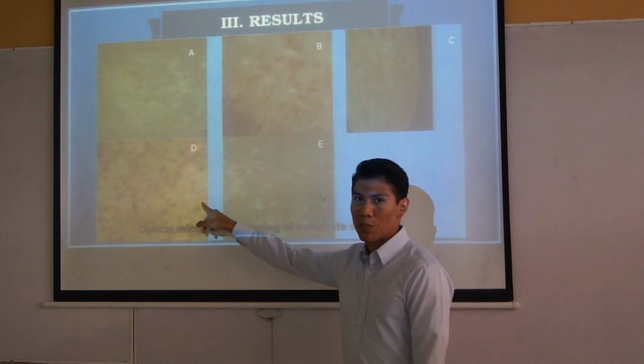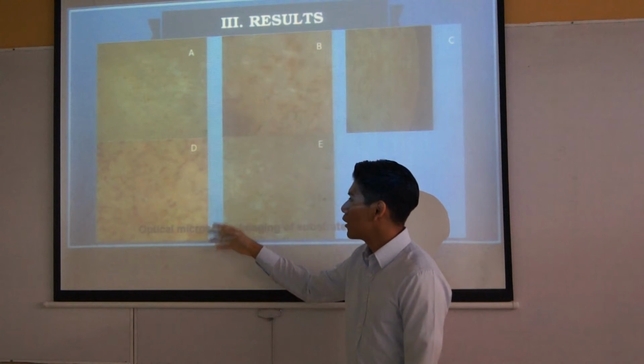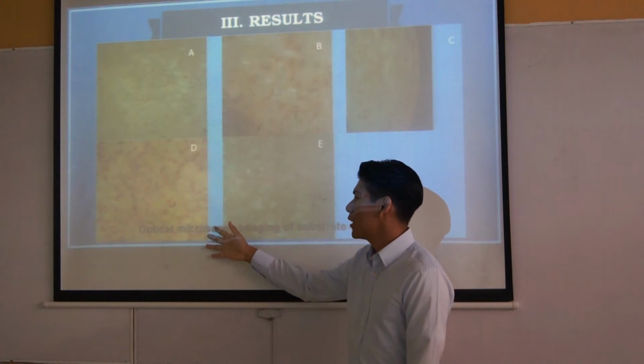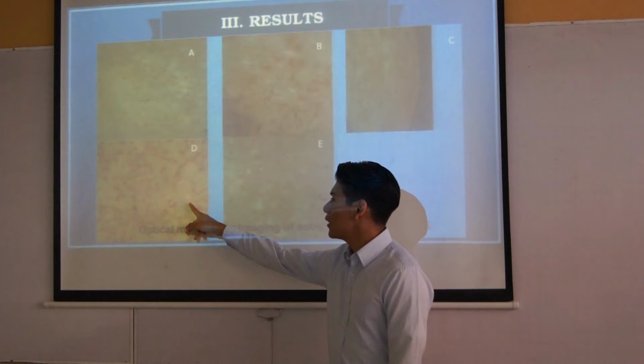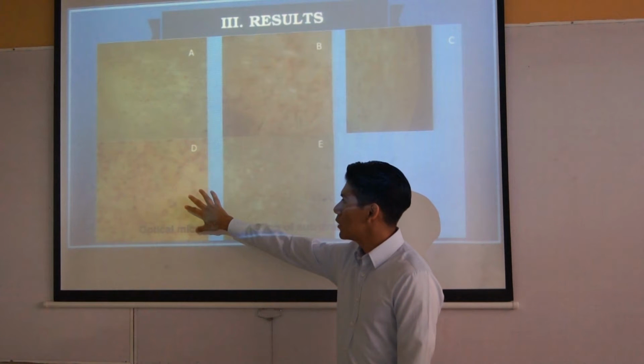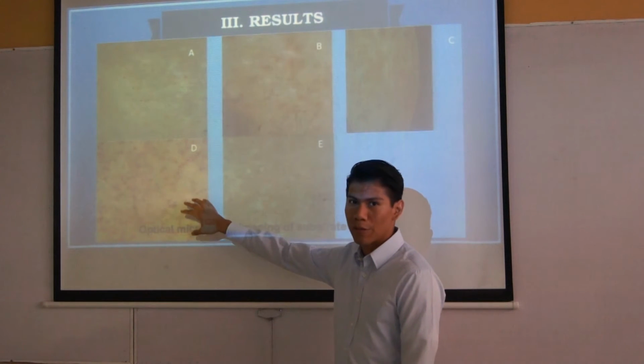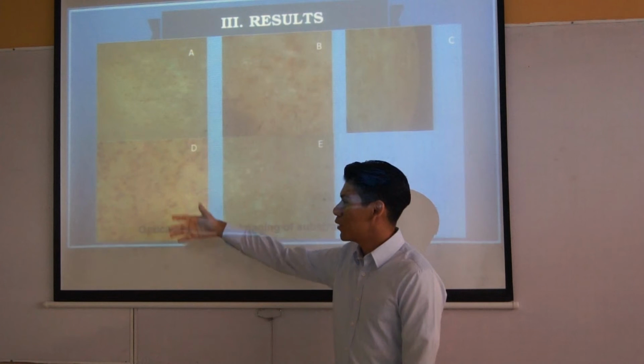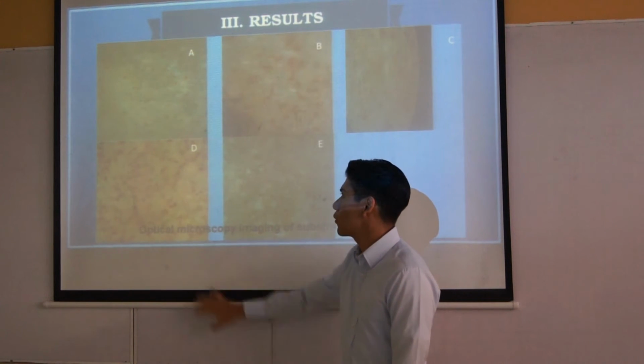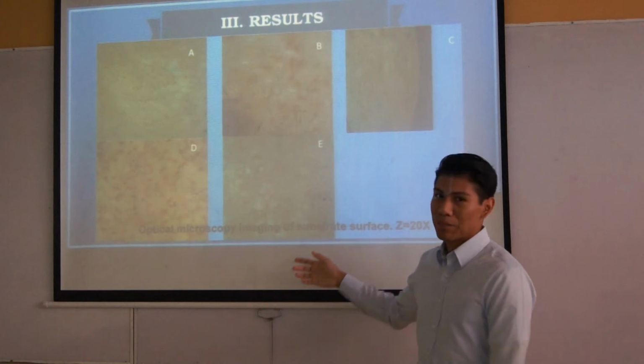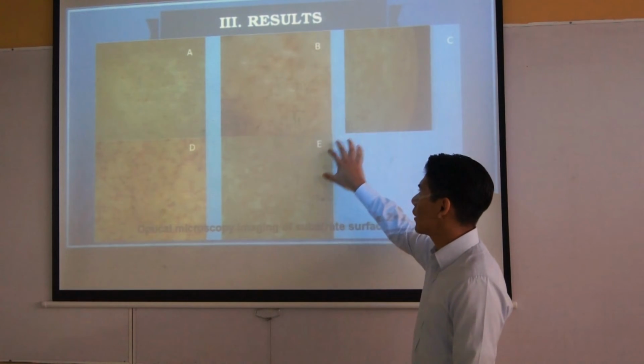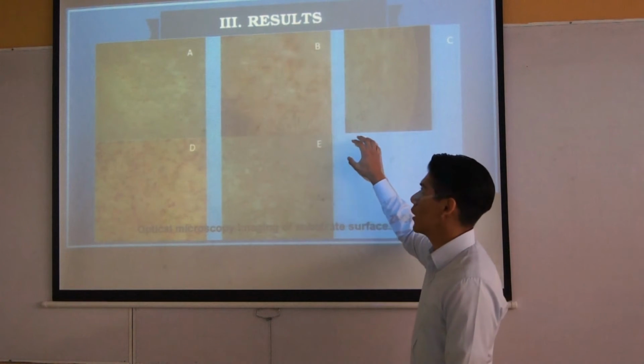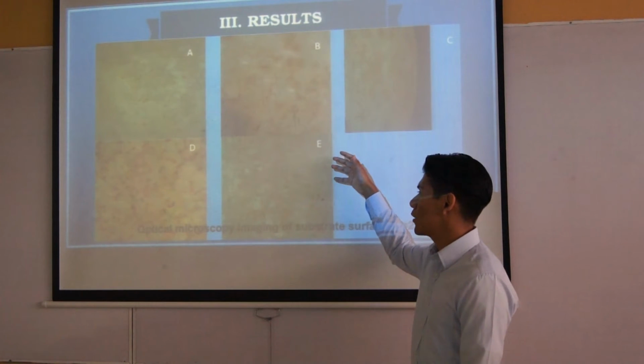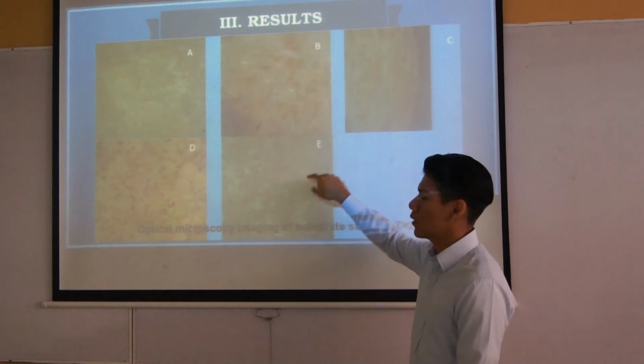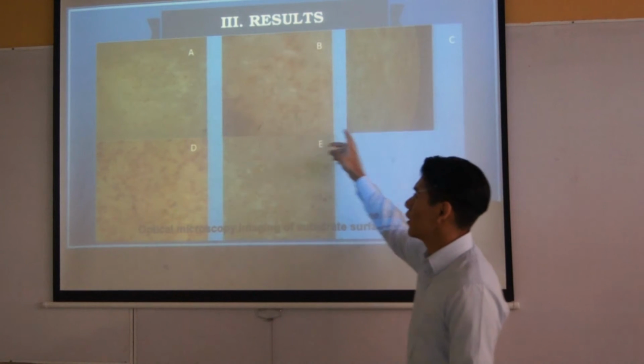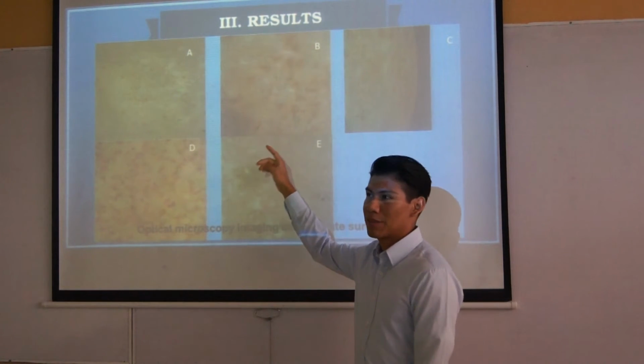But when we observe probe D, we see that there's a lot of dead material, organic dead material, and there's no attachment of the cells, because these cells that we observe here, the form, the shape, are on the background. They're not really attached to the surface. So what we can maybe conclude from here is that the substrates containing hydroxyapatite are acting as bioactive surfaces because the cells are attached. Whereas in the other substrates, they're not.